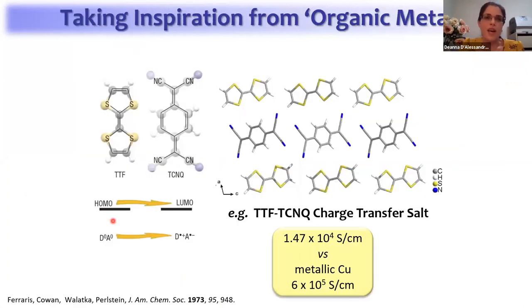So I wanted to give you an example of how we use these types of techniques, and we've taken great inspiration from this historically rich area known as the organic metals. A number of these types of materials are even superconducting, and the idea is that we match the donor, in this case a tetrathiafulvalene, and the acceptor, in this case a TCNQ, and we match their potentials, if you like. And what is interesting about these purely organic materials is that they have very high conductivities, even almost on par with that for metallic copper itself.